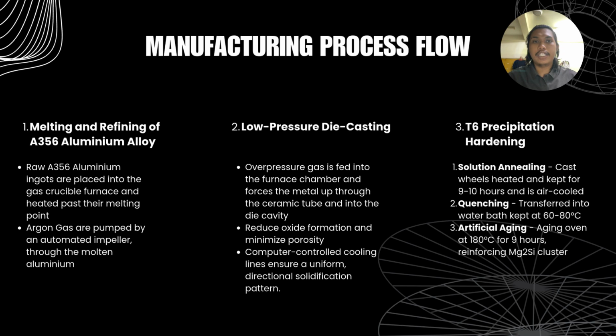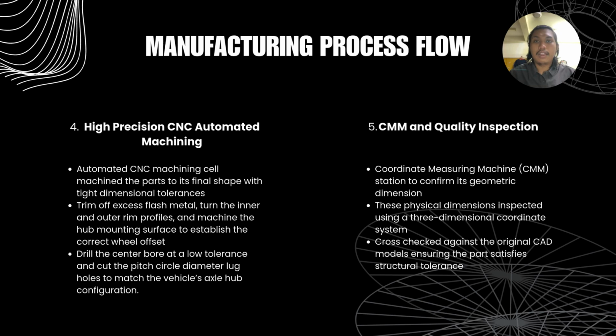The second step is quenching, where it is transferred into a water bath kept at 60 to 80 degrees Celsius. This rapid cooling locks the dissolved alloying elements into a supersaturated state at room temperature. The final step is artificial aging, where it is placed inside an aging oven at 180 degrees Celsius for 9 hours, reinforcing the magnesium 2 silicon cluster within the aluminium grain, thus significantly increasing the wheel's yield strength and structural rigidity. The next process is high precision CNC automated machining.